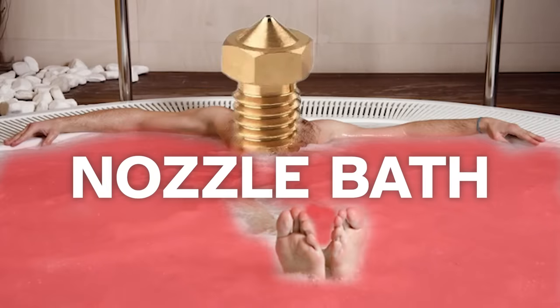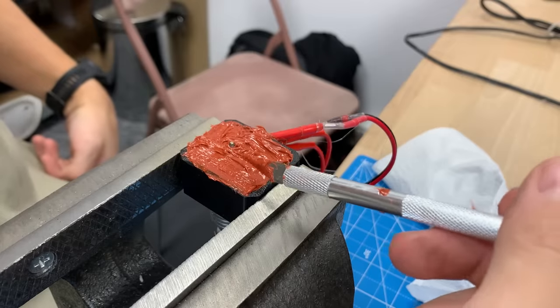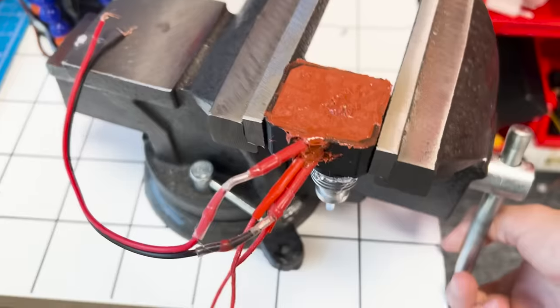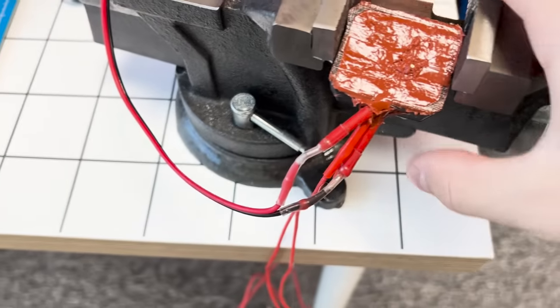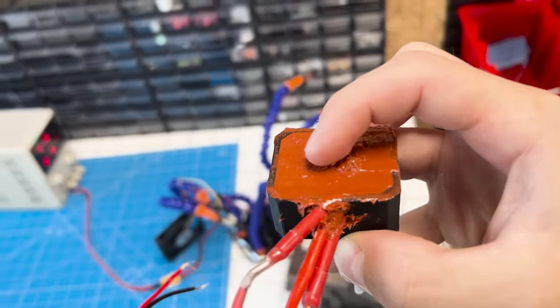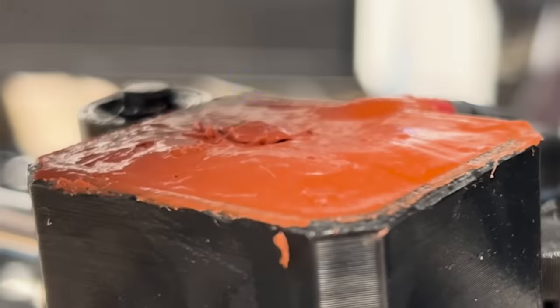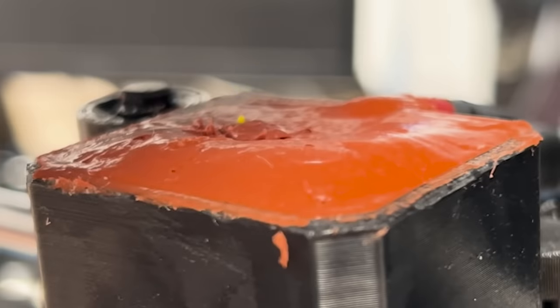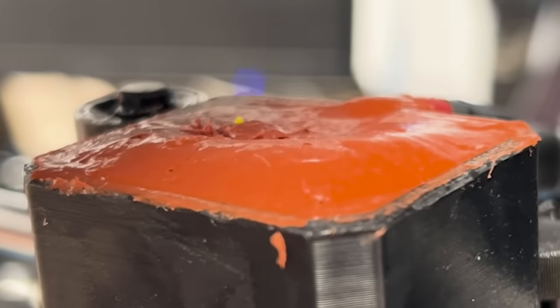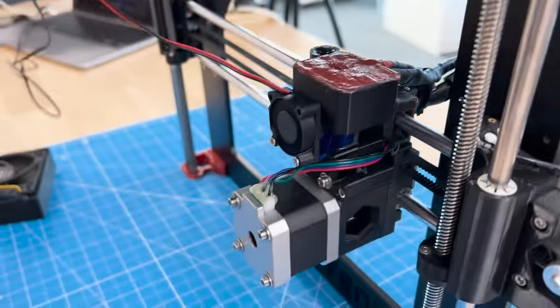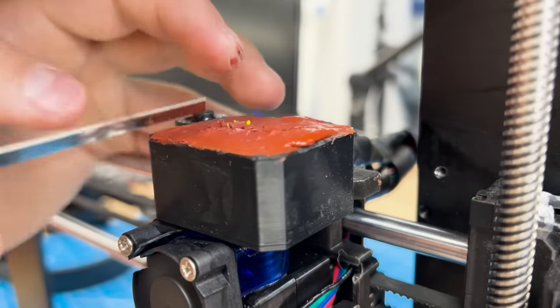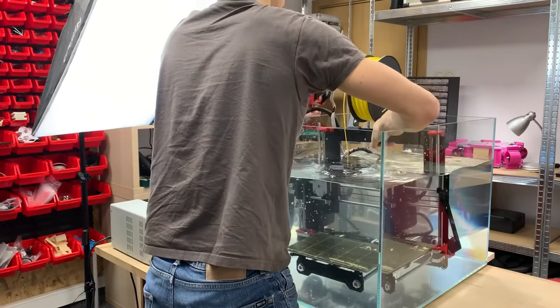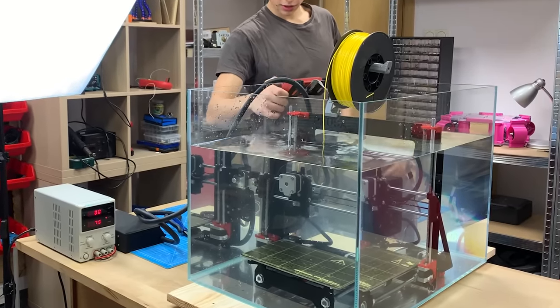It's a lot less liquid than the previous one. It's like Nutella, look. Unfortunately, after we came back three days later, the silicone was still soft on the inside. And when it heated up, it expanded and started to protrude below the nozzle level, which makes it unusable. Now we can cut it. So we cut it. We are ready for the first ever proper underwater print.